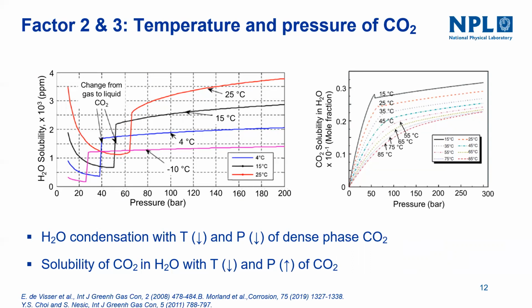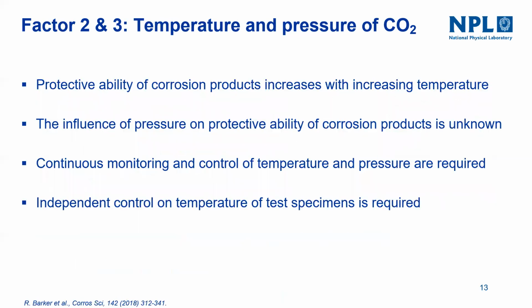And the second thing is the pressure. Normally with a decrease in temperature, the CO2 solubility in water increases, and similarly for the gaseous impurities. What this tells us is that the higher the solubility of the CO2 or the gaseous impurities in water, the more the corrosivity of the condensed water increases. And temperature and pressure can also play a role in the corrosion rates.